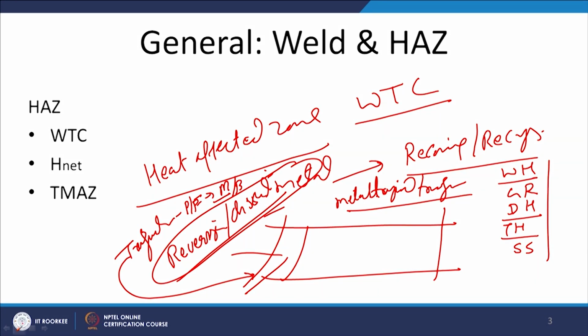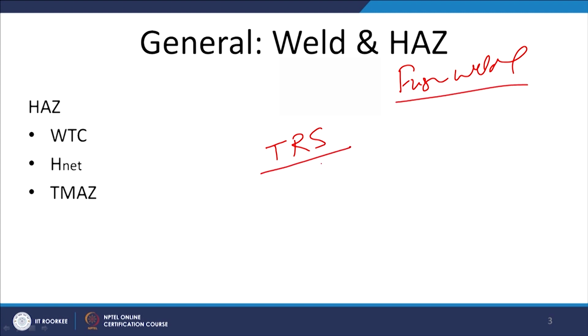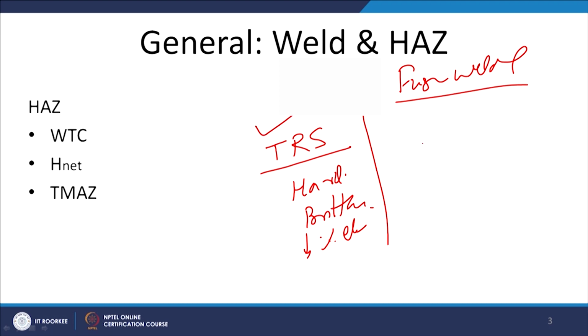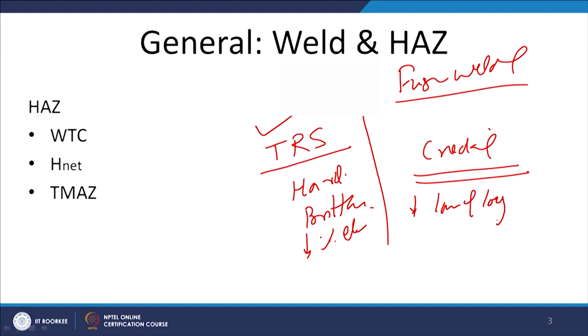Apart from these, the heat affected zone also experiences, in the case of fusion welding processes, tensile residual stresses. So, if the metal system is hard, brittle, with low percentage elongation, then tensile residual stresses sometimes lead to cracking in the heat affected zone. It also leads to the loss of toughness.